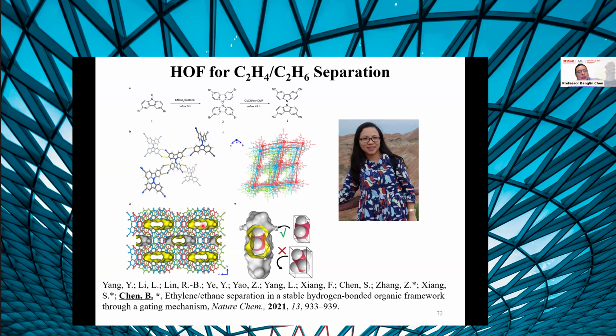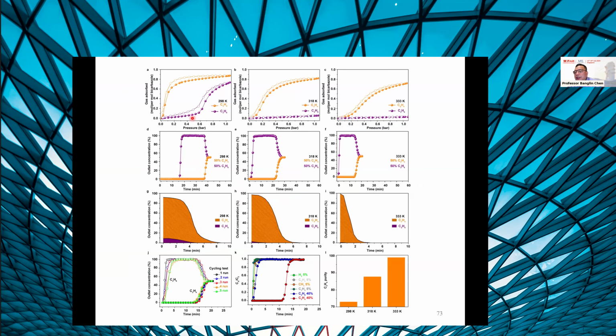Furthermore, the material shows a flexible and robust framework and good separation performance. When we increase the temperature, the uptake of ethane decreases slightly. However, the uptake of ethylene decreases significantly, and in that case, the C2 separation performance is unbelievably good. So at moderate, higher temperature, we are able to purify and get high purity ethylene. So this is very good.